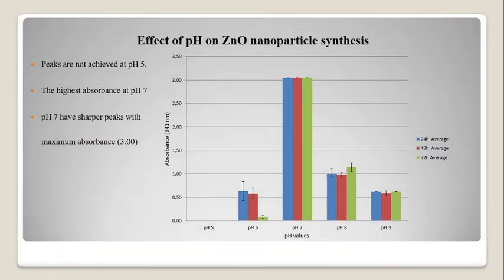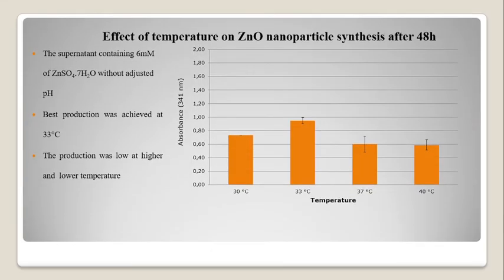Effect of pH on zinc oxide nanoparticles. pH 7 has sharper peaks with the maximum absorbance of 3. As we see here, for all days, pH 7 was higher than the others. Effect of temperature on zinc oxide nanoparticles. Best production was achieved at 33 centigrade.